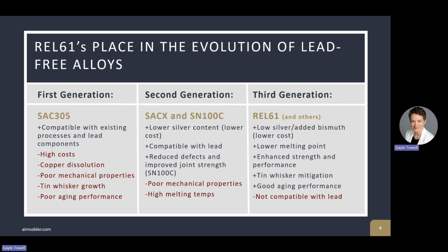There are third generation lead-free alloys, and there are many alloys in this category. Our REL61 alloy fits within this category. It is a low silver alloy, but it also has bismuth added, so it is lower cost. The addition of the bismuth actually lowers the melting point a little bit. It has improved strength and performance, seems to mitigate tin whisker formation, and has very good aging performance. The one major drawback of this alloy, however, is due to its bismuth content. It's not compatible with any processes that still have lead in them.